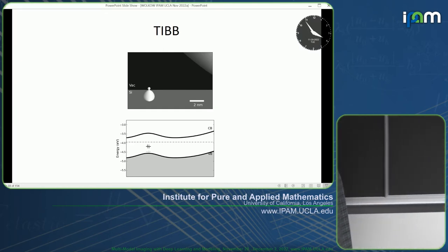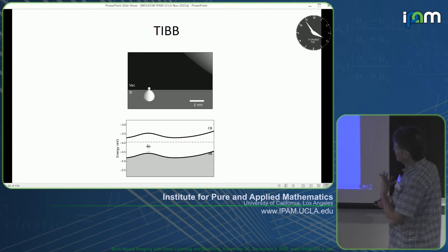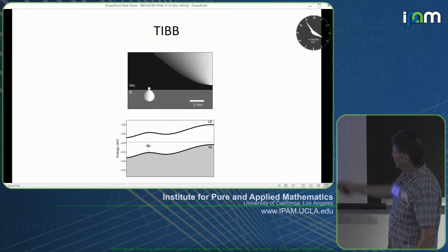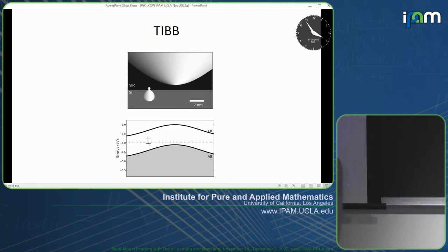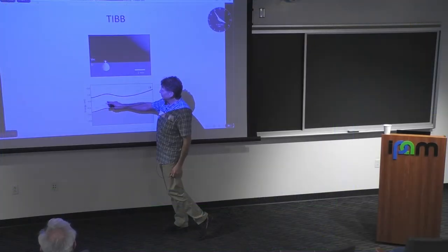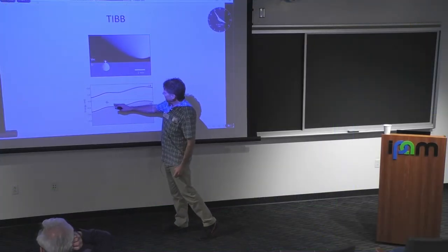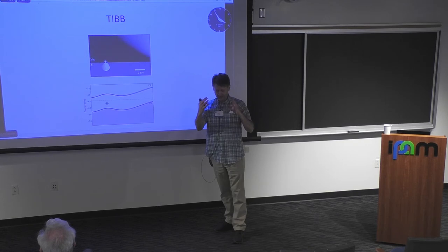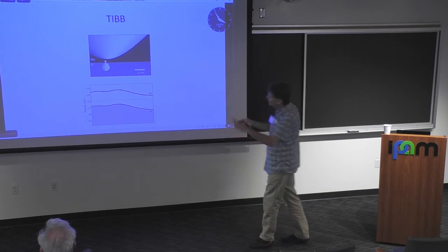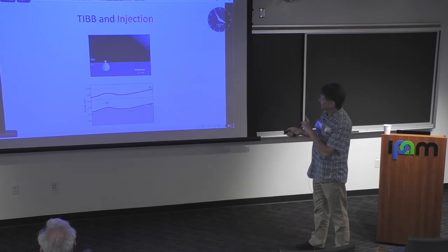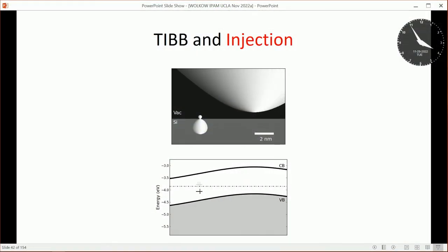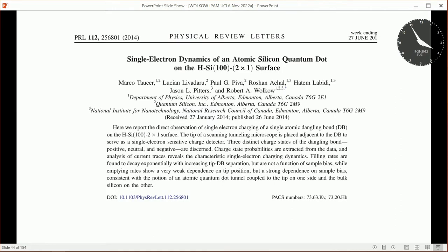If we make these dangling bonds, we see that the very identically same structure can look wildly different depending on the doping level. And I'm just going to say now that we understand that. I have to go faster. Basically if you have a Fermi level that's near or in the conduction band, you essentially force electrons to fill this what would nominally be a neutral state. If you have an intrinsic material, you have just one electron. If you have a p-type material, you'll have a positive dangling bond. And these have ramifications in the images. Very quickly, this is just like a field effect transistor. Here's our atom, our dangling bond. Here's a probe, think of it as a gate that is moving. It moves along and it bends bands, just like in your textbook. But look at those beautiful things that happen. As you shift an occupied state above the Fermi level, an electron must fall out. And the very moment that falls out, the bands drop back down because you've just taken away a negative charge and gone to neutral. So you've removed this upward band bending. So it's a kind of positive feedback effect. It's more complicated because we've left out some steps, but then we can put those in. I don't expect you to absorb all this now, I just want to say we understand it.